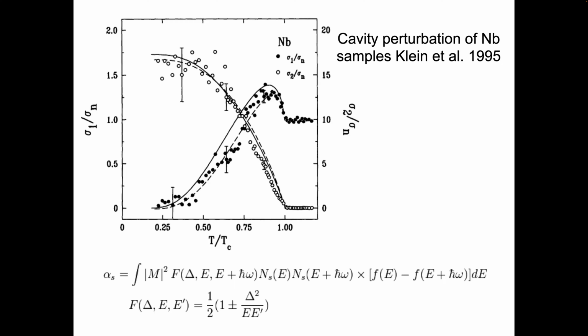The real part, which is the dissipative part, has this notable peak near TC, and then it comes down and is exponentially suppressed in an S-wave superconductor. This peak near TC is what we might call, it's not generally called this in optics, but it's really the same thing, a Hebel-Slichter peak. And so Hebel and Slichter, Slichter was a professor at the University of Illinois. Hebel was his graduate student. And it was, in the early days of superconductivity, one of the first real results for the kind of interesting details that gave a feeling about the microscopic BCS theory of superconductivity.